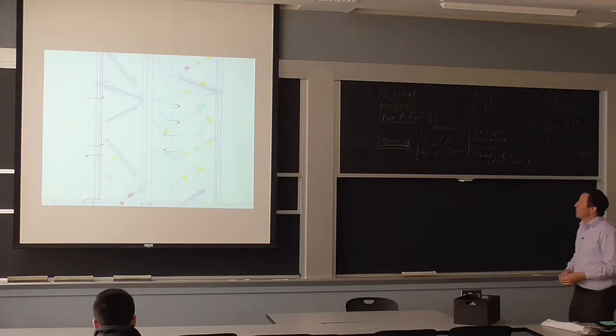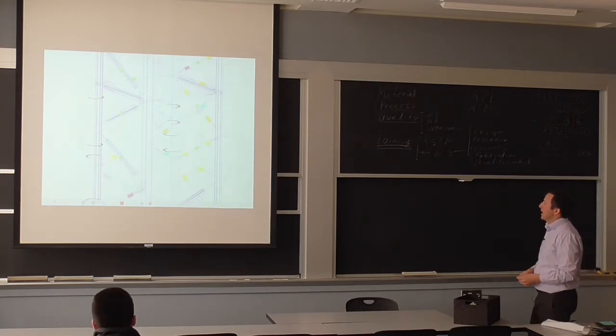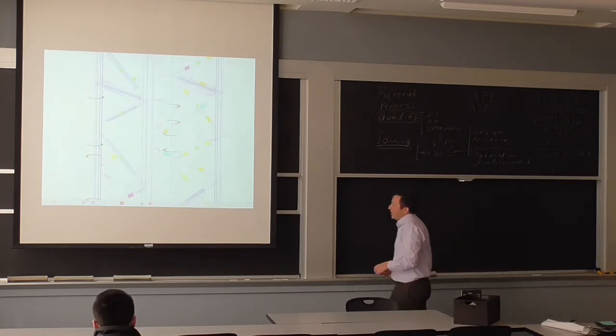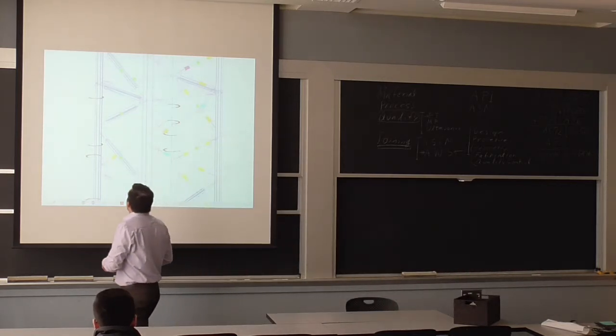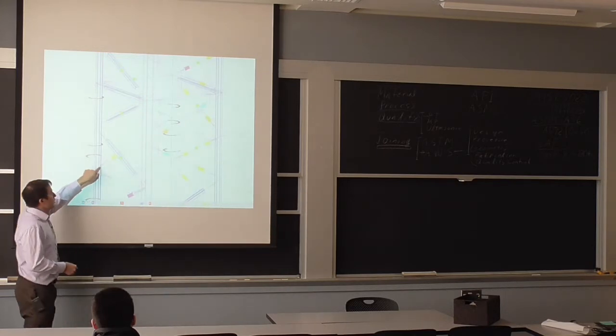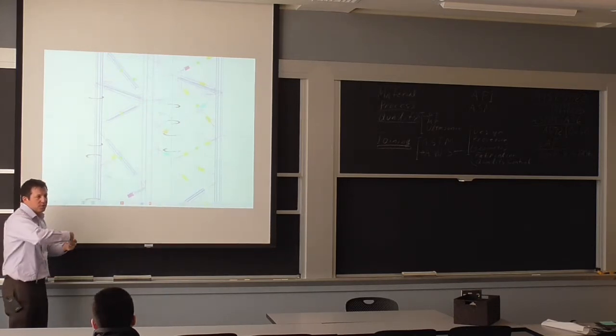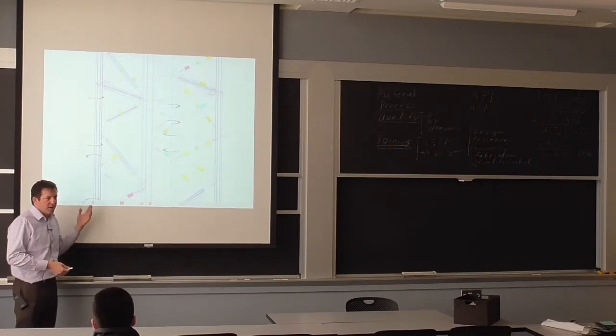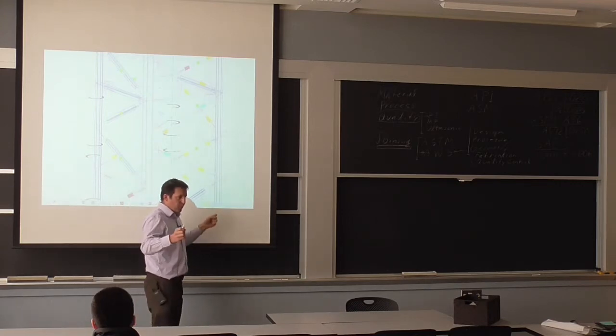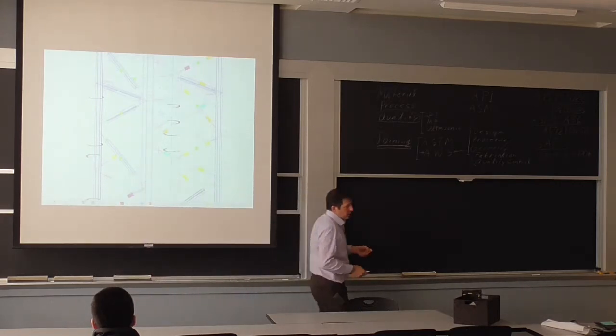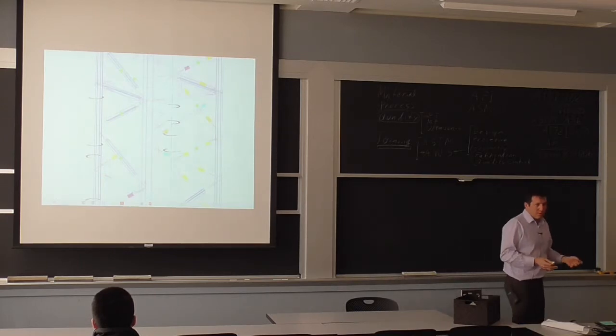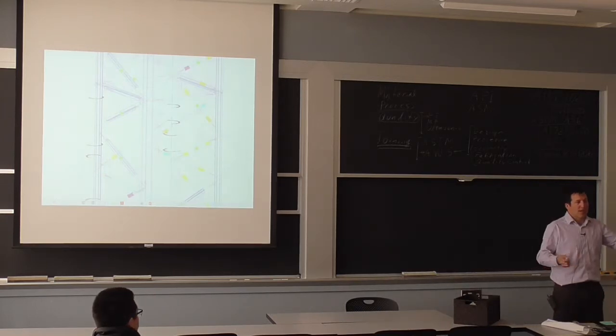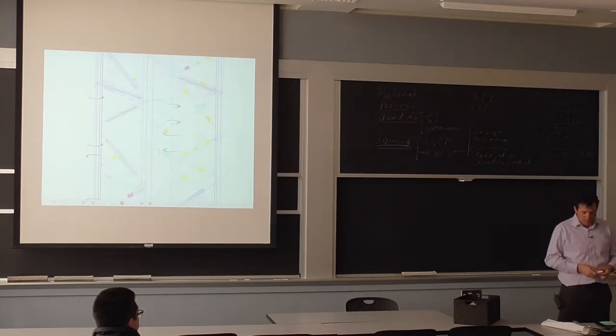So over here, I just show a little bit of a diagram where just by going through the debris, we created an inventory of how each connection failed. Is it just a pull? Is it just bent? Because if it's bent or crushed, that's a consequential effect. The most likely thing to start here is just a straight pull. So we were essentially looking for straight tubes that were just pulled out without anything else, because that's where it's more likely to break, especially because you'll see there were a bunch of welded connections.